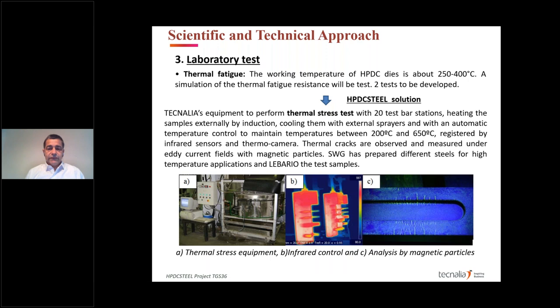So once we have defined which are the alloys and which are the compositions that we want to study, we have defined the way that we measure and study at the laboratory scale and after that at the industrial scale to test this material. So, thermal fatigue is related to more or less 80% of the cracks in the dies. So in Tecnalia, we have a machine to try to simulate the behavior of the thermal fatigue by heating, by induction, some test bars from 200 to 650 degrees in a continuous cycle. With different test bars, we can make a simulation of how a core is working in a die.